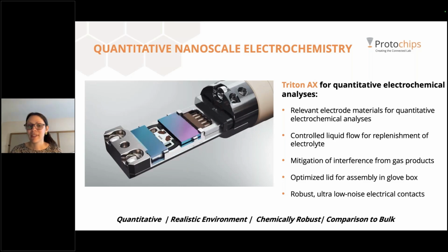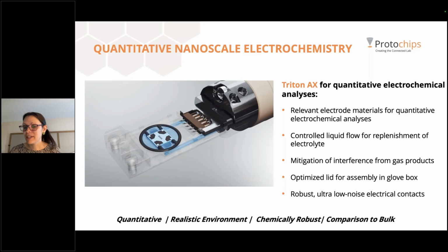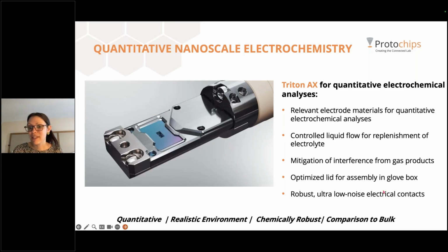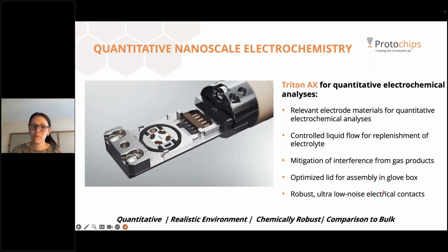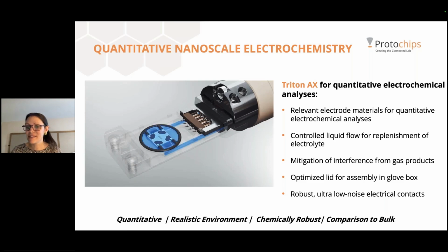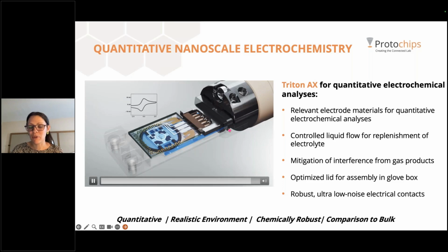The design of the chips and the design of the holder ensure controlled liquid flow for the replenishment of the electrolyte. You have to walk a very fine line with liquid electrochemistry and make sure you have enough electrolyte for good signal to noise, but you also want to control the thickness of it for better imaging resolution. And so with our chip designs and our holder design, you're able to do that. Mitigation of the interference from gas products. Some of these experiments produce gases, bubbles, and sometimes you accidentally produce bubbles. You're not supposed to. If you do, you need to be able to remove them, which again, the design of the chips here enables the removal of those.